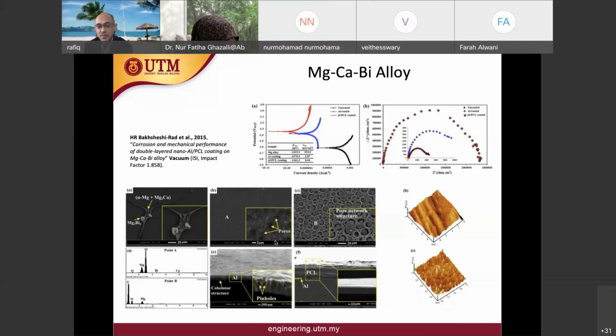Well, yes, we managed to develop this type of alloy, magnesium calcium bismuth alloy, and then in order to improve its degradation rate or prevent it from degrading easily, we coat with nano aluminium and PCL, polycaprolactone. And these are the results.